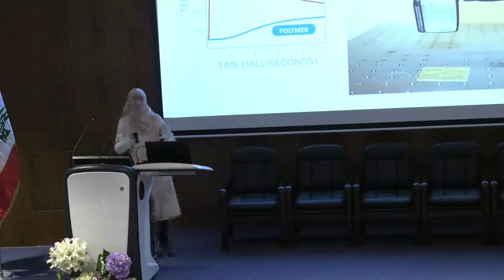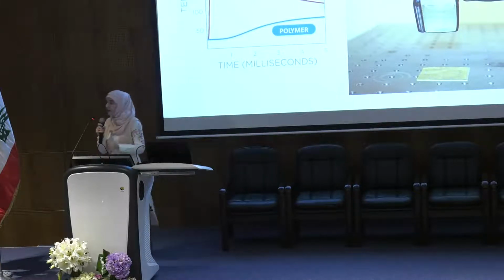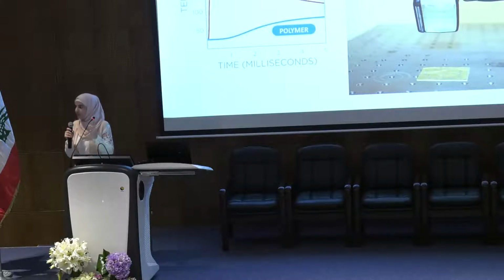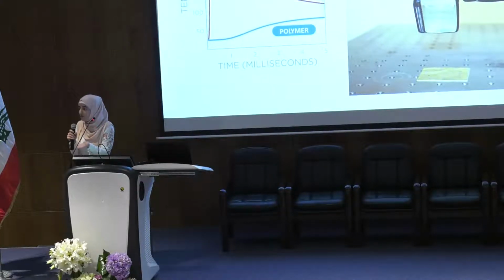This is because, as I mentioned, the polymer has a low melting temperature. For the PCL, it is 60 degrees. So when we want to cure the ink, we need 250 degrees. If we put the overall device inside the oven at 250 degrees, the PCL substrate will biodegrade and the pattern will be destroyed. So we don't want this. That's why we are using the camera flashlight. It's going to increase the temperature instantly within a few milliseconds. This technique will not degrade the substrate. It will only cure the ink.